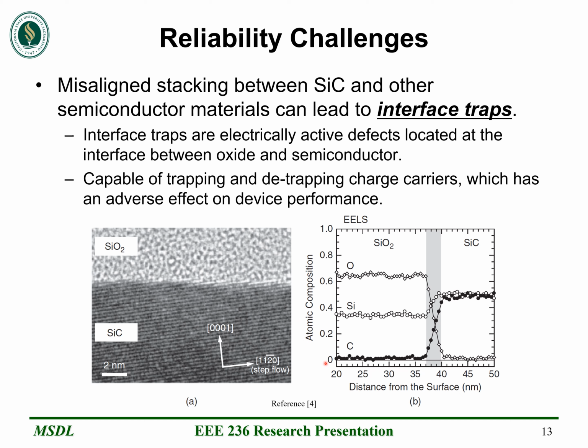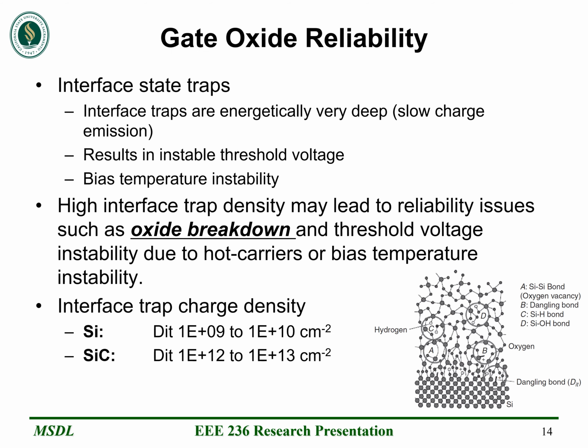Another plot on the right shows the atomic composition as a function of the distance from the surface, moving from silicon dioxide to silicon carbide. These interface traps would occur more likely at this transition region. Now let's take a closer look at gate oxide reliability for silicon carbide. Gate oxide reliability has been the most prevalent problem when it comes to fabricating silicon carbide microelectronics. And the reason being is that silicon carbide has a very high interface trap density.